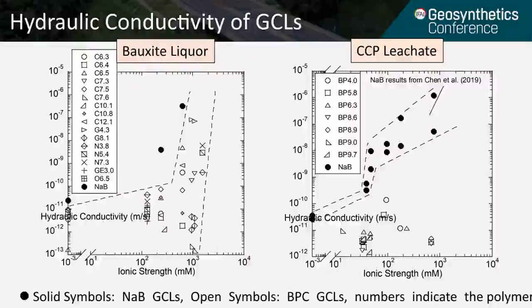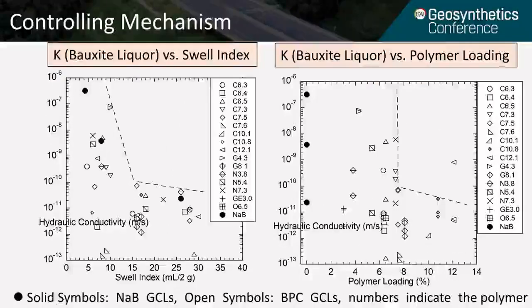Still, there are some increase in hydraulic conductivity at a high ionic strength range for bauxite liquor. I will cover this in the mechanism discussion. So we want to understand the controlling mechanism of these GCLs. Especially first, we compare the hydraulic conductivity with the swell index. So as we expected, the hydraulic conductivity is not correlated with swell index. This is in consistency with our previous study.